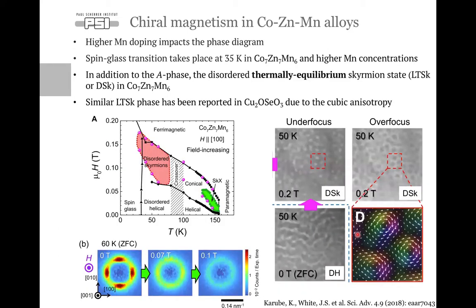But other interesting things happen as we go to higher manganese compositions, where the manganese doping impacts the phase diagram dramatically. First of all, we have the A phase, which is just below TC, which is typical for other cobalt zinc manganese materials with lower manganese content, and also typical for other cubic chiral compounds like copper oxide selenite (Cu2OSeO3) or B20 materials. So this A phase is attached directly to the paramagnetic phase, and the skyrmion lattice pops up in finite magnetic fields and in a narrow pocket just below the TC.